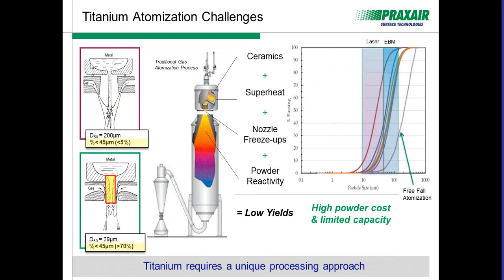When you use that, it's a very clean melting technology, but it prevents you from adding superheat to the liquid. Therefore, you have to really be careful about how quickly you strike that liquid with gas. If you don't add enough superheat, for example down here, and you use the close coupled technology, you're going to freeze that liquid out right away, and that's what we call nozzle freeze-ups. And then you have to start over. You have to go in, remove the metal, reload it. It becomes quite a pain and very low productivity.